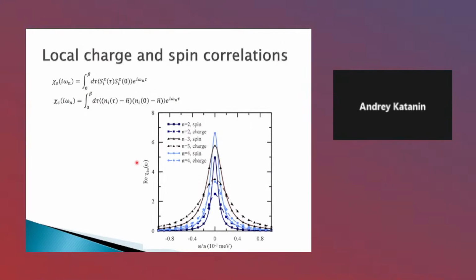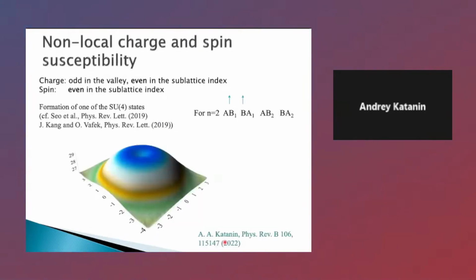We also calculate the local charge and spin spectral susceptibilities. One sees these narrow peaks of the order of 10 to the minus 2 meV, which show that the charge and spin degrees of freedom are strongly localized at integer fillings, which are considered here. And finally, we consider the non-local charge and spin susceptibility. We find that charge susceptibility is odd in valley and even in sublattice index, and spin susceptibility is even in the sublattice index.